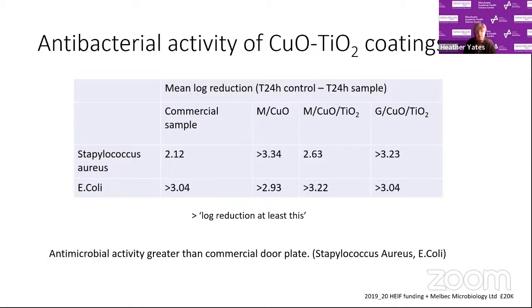You can see, the M is metal, the G is glass, that on glass, generally speaking, it works slightly better. But what we can see, because we also took a commercial sample, a door plate that was advertised as being antimicrobial, and you can see the numbers there are lower. So my research samples work better than the commercial door plate for these materials.